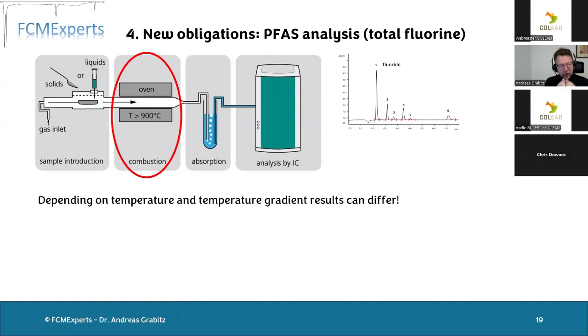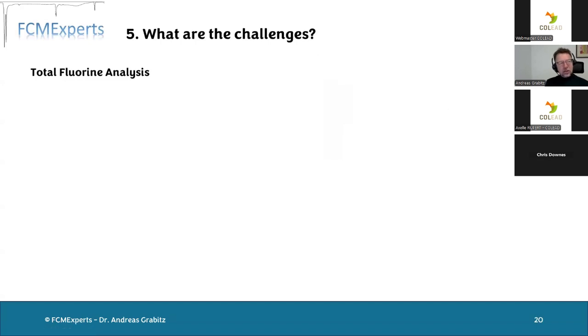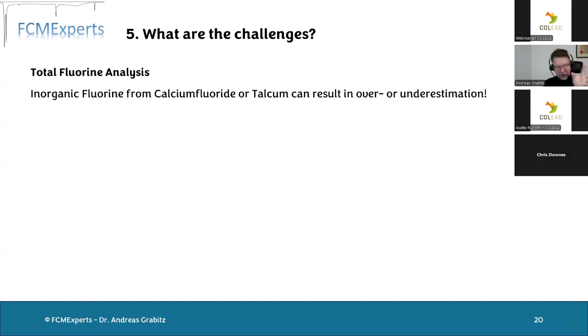So one of the critical points here is that depending on the temperature and the temperature gradient, the results can significantly differ. So this step here is really the critical point, the combustion step, where we burn or incinerate the sample. And this brings me to the challenges. So when we go for the total fluorine analysis, we have partly the problem that we can have an over or an underestimation when there are fluorine salts in the sample. Then this can lead to an over or an underestimation.